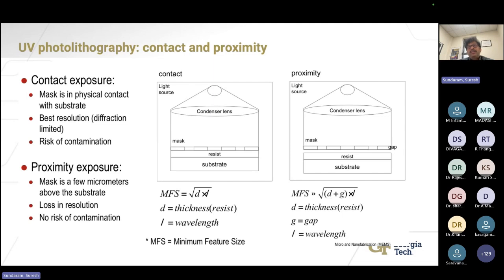For extreme UV lithography, we are using 13.5 nanometer, which gives us 3 nanometer feature size. There are a lot of other optimizations also involved, but the major factor that affects the feature size is the wavelength you are using. In proximity mode, the minimum feature size is approximately equal to the root of (d plus g) times L, L being the wavelength.